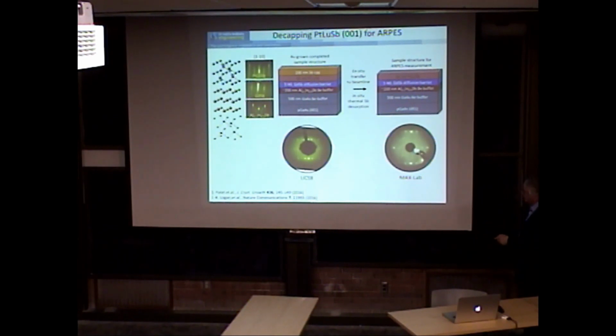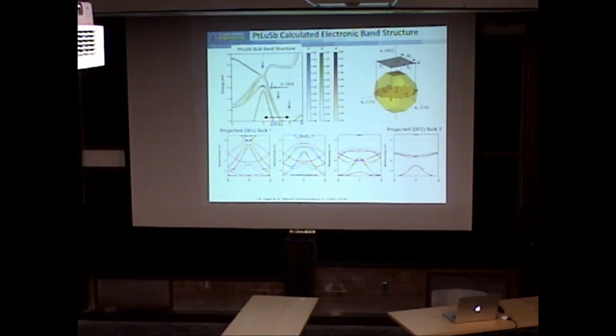And here's a LEED pattern taken at UCSB before we capped. Here's a LEED pattern with a slightly different LEED system done at Max Lab after we removed the cap. And then you can look and see, do you see oxygen, carbon, or anything else on the surface? But we can actually see from the diffraction pattern, we've got the same film. Okay, so what is it we're really wanting to do? We're going to now change photon energy. If you change the photon energy, we can actually look at this calculated band structure, where we see the S states down here.